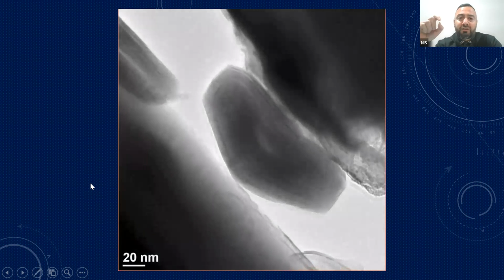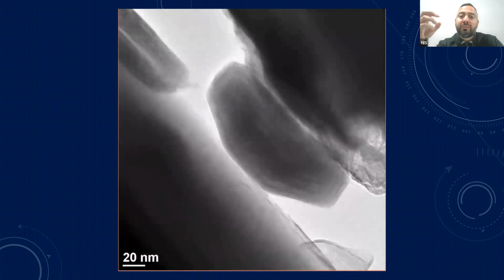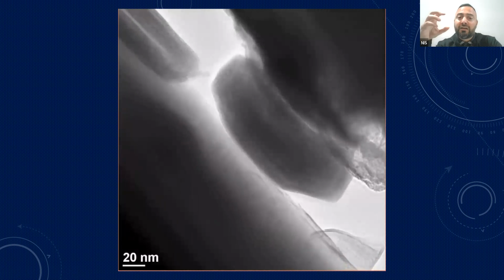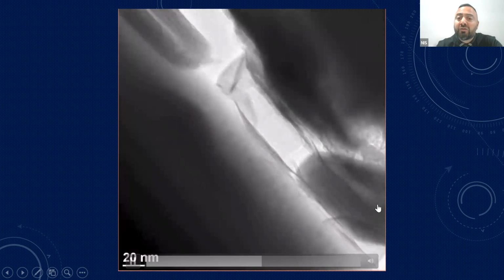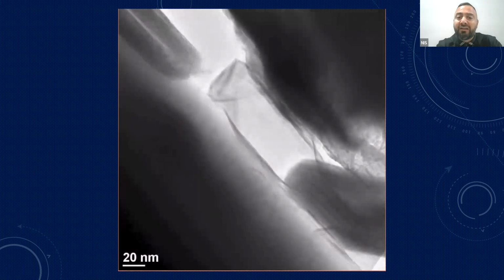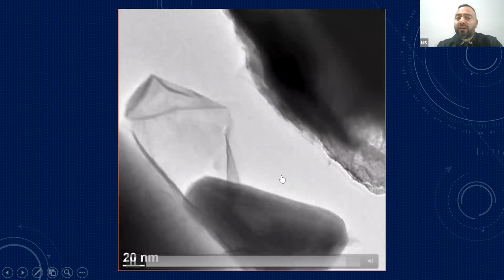So you see that they're compressing the particle, and this particle is changing its shape. So it absorbs the shock, it gets compressed, and at a certain point, the outer layers of this tungsten disulfide particle get exfoliated. The moment of exfoliation, that's your friction reduction mechanism. You can notice that the actual particle went back near its original shape, so it's bouncy. It absorbs the shock, preventing micro-pitting and galling. The layers that got exfoliated are very adhesive and extremely strong because it's tungsten. So it adheres to the surface, creating an anti-wear coating on the surface, as well as reconditioning the surface. And this particle is again ready to produce more exfoliated layers like this. And it goes on and on.